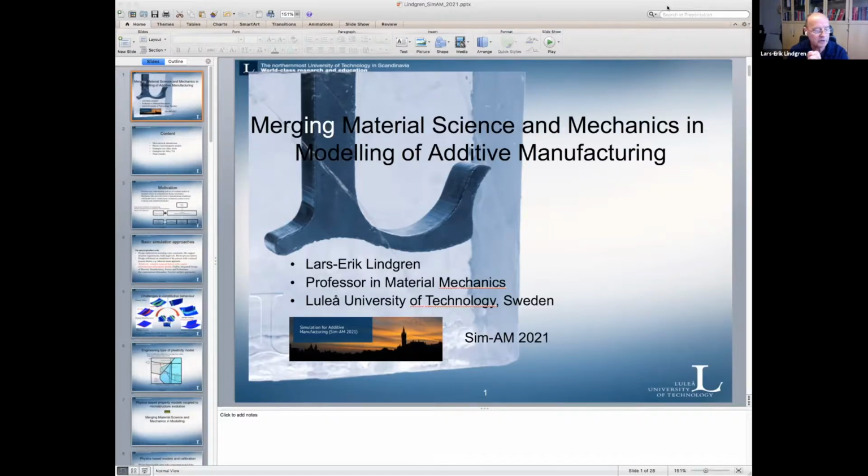Regarding non-equilibrium, some of these models do include non-equilibrium. Of course, the phase change model is based on that. The one for the steel is more ad hoc, but the one for the precipitate growth is a non-equilibrium one, where you have a driver to minimize Gibbs energy that gives the growth of the precipitate.